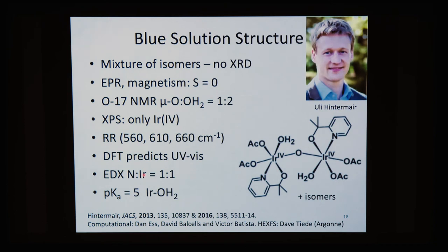So the blue solution structure was looked into by Uli. He showed that it was a mixture of isomers, and that's why we couldn't get crystals. EPR and magnetism were consistent with diamagnetic. O17 NMR showed the bridging oxygen to water ratio to be 1:2. The XPS showed iridium 4. Resonance Raman was consistent with a bridging oxo. The DFT modeled the UV-Vis spectrum, and the EDX gave a nitrogen to iridium ratio of 1:1. And then a pKa of 5 was associated, we thought, with one of the waters bound to iridium.